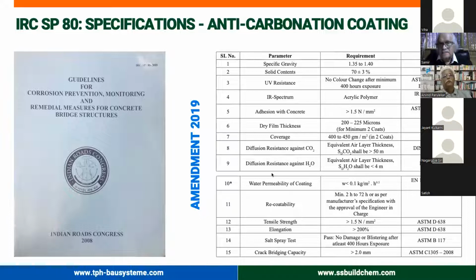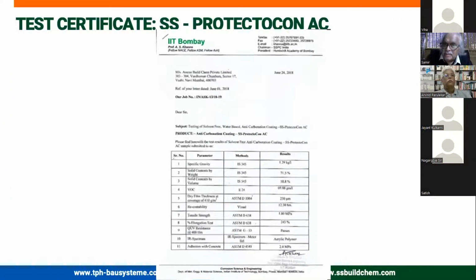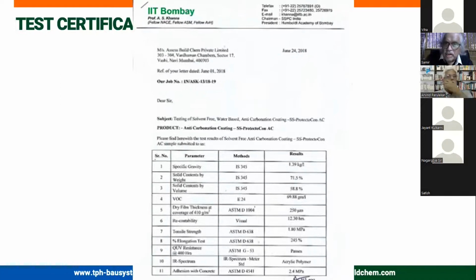15 properties. From the specific gravity, from the thickness of the coating, from the dry film thickness, from its solid content, from its type, from the color changing, from the recoatability, the tensile strength, very important, elongation, salt spray test for chlorides and crack bridging capacity. Diffusion against carbon dioxide, which is most important, it should be more than 50. Breathing capacity, it should be less than 4. When you have the codes, then why let a professor of English write your specification?